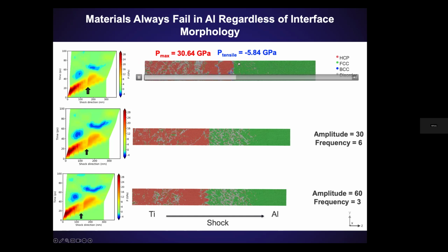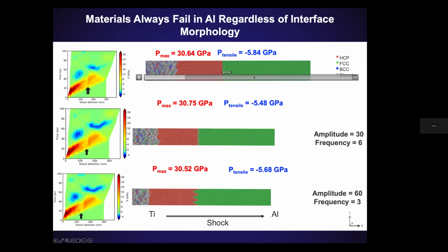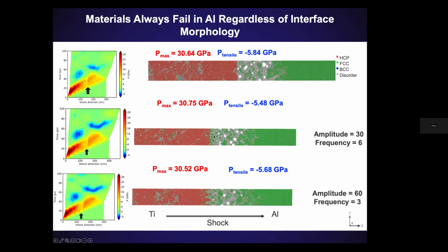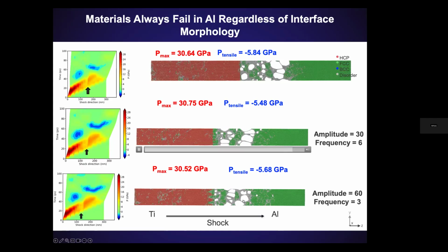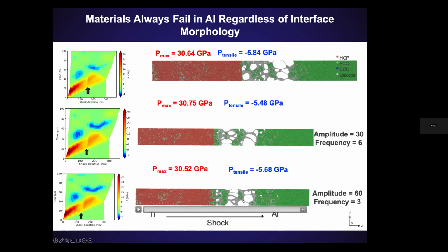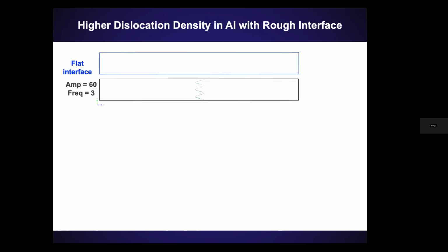So if you look, shocks coming in, defects are nucleating, you form voids on the aluminum side. And you know what? Regardless of that interface roughness, you always form voids in the aluminum side. We designed these simulations so the region of maximum tension will be at the interface. But in molecular dynamics, the interface is apparently stronger than aluminum. So no matter what you do, you form damage in aluminum.